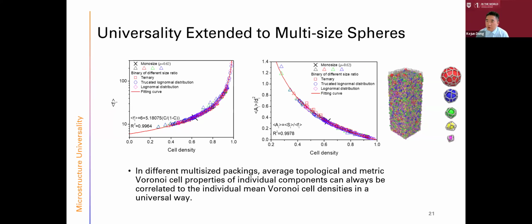And the microstructure universality we find can also be extended to multi-size spheres. So we also did a lot of different multi-size sphere packings. And what we can find is their partial mean value, which means in a multi-size packing, we have a component with a specific particle size, and we extract all these particles and do the analysis of their properties. Then their properties, like the mean value and the standard deviation, can be correlated to their mean packing fraction, which is obtained from their Voronoi mean value. Okay, that's another extension.